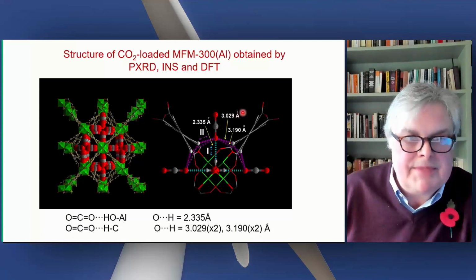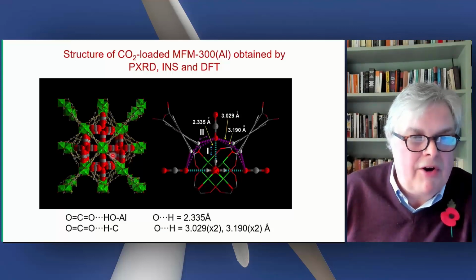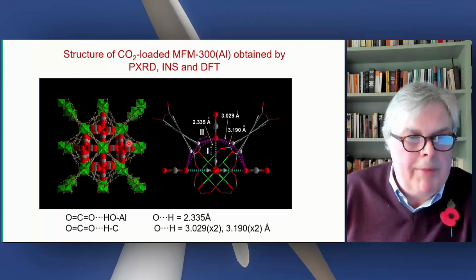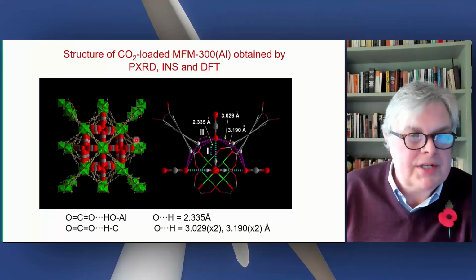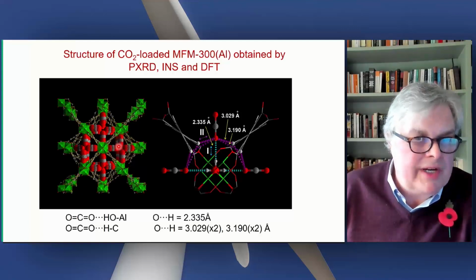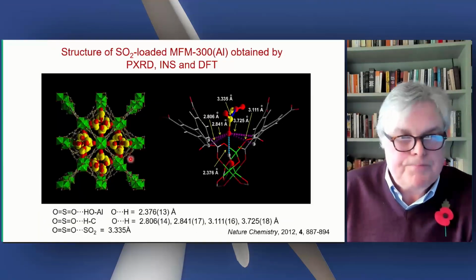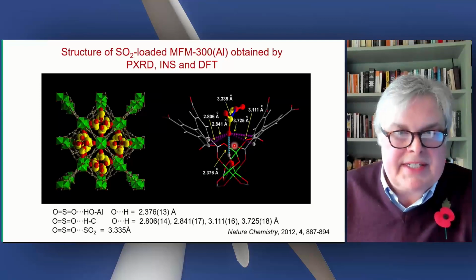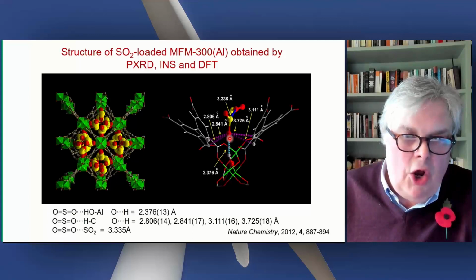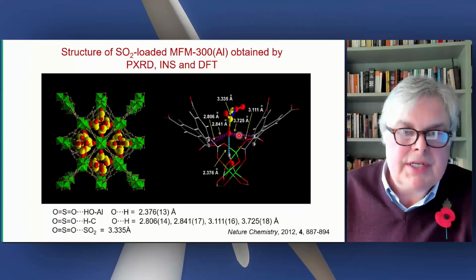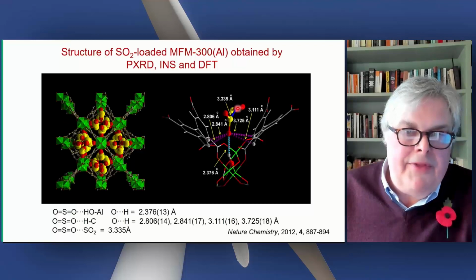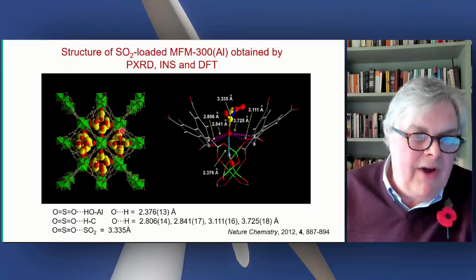The next CO2 comes in at perpendicular, links into that CO2, and then fits into this pocket really very nicely. So you can see there's really good complementarity between the substrate and the host pore, the substrate fitting very nicely into that pore. SO2 is very similar in the sense that, again, you have this OH interaction. There's the aluminium, very nice interaction, hydrogen bond there, and then 4 further CH interactions. SO2 actually forms a dimer. The oxygen from another SO2 comes in, interacts with the sulfur, and you can see very, very good packing.